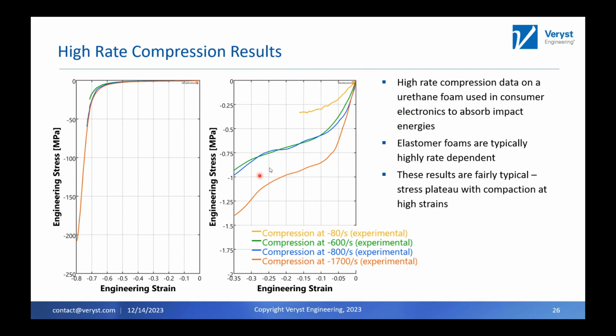here we did test it for rates. One downside of the system is that for some of the lower rates we can't get to the really high strains because the rate is tied intrinsically to the pressure that we applied and the energy that we put in the system. So we were only able to go up to about 15% strain at this lowest rate. But at these other higher rates, you can see that we're getting compaction up to 70, 80% strain. And you see a couple of effects. The compaction here is basically on top of each other, but you have a different small strain response where you're getting stiffer and stiffer. That plateau stress increases.